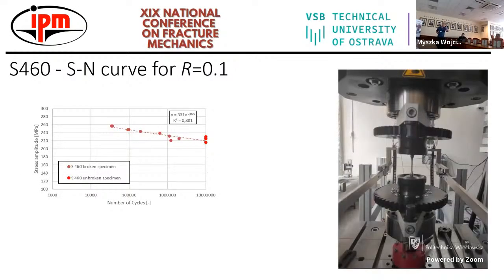We move on. The other step is the information about the SN curves. All our measurements we perform at the stress ratio 0.1, which is an important stress ratio for civil engineering structures. You can see that the information is very homogeneous. The index of dispersion is 0.8, and here you can see the specimen which is unbroken at this level, 220. It means that, according to the stress ratio 0.1, it is approximately 440 or 450. It is the limit for the cyclic load.